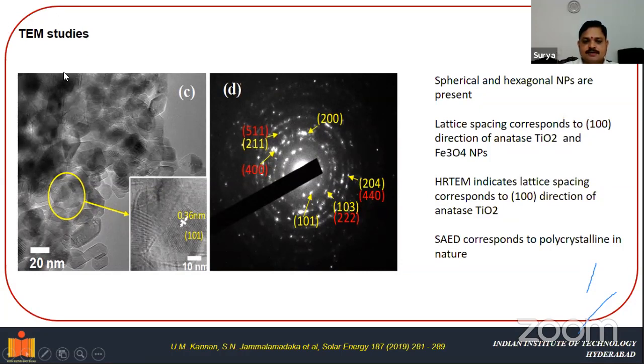We wanted to prove that our material is in the crystalline phase, and you can see that in the TEM micrograph of the titanium dioxide, we have spherical and hexagonal nanoparticles present. You can see the shape of the nanoparticles is spherical, and they also have the hexagonal structure. The lattice spacing corresponds to the 100 direction of anatase TiO2 and Fe3O4 nanoparticles. For instance, if we see the diffraction patterns, if you expand this region, you can see the lattice planes. From the TEM, we have crystal clear lattice